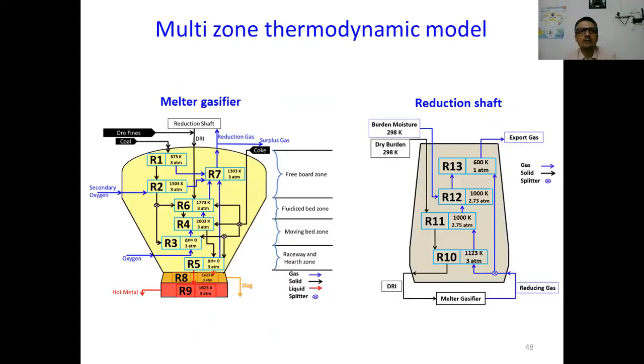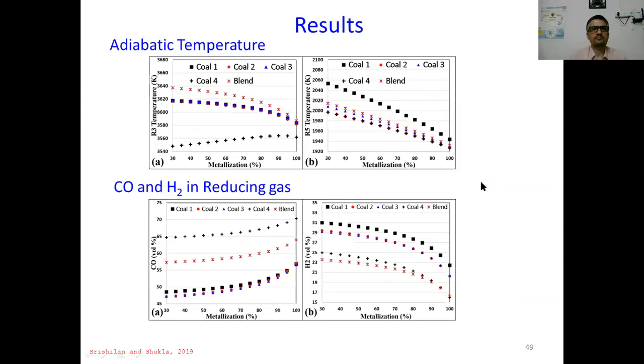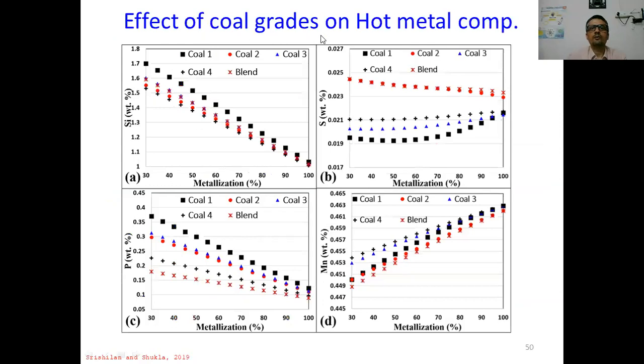Then the multi-zone thermodynamic model has been developed, where the process has been divided into a number of zones, and similarly the reduction shaft has also been divided into a number of zones. Based upon that we made certain calculations of adiabatic flame temperature, CO/CO2 requirement in the reducing gas, and the effect of coal type on the hot metal composition. So different types of coal have been used. I don't know which is the superior coal, maybe we can find out. Of course, in general, as the metallization increases, the silicon percentage also decreases.